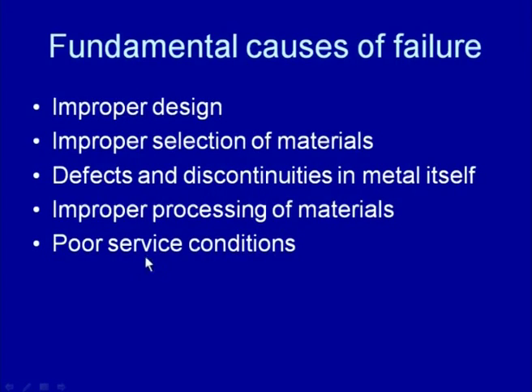Then there are poor service conditions. A component can fail if it is exposed to conditions for which it has not been designed. For example, a mild steel weld joint can be successfully used under normal ambient conditions, but if it is used under sub-zero conditions, below minus 20 degree centigrade, then it will show a great reduction in toughness, and it can fail in a very brittle manner and will not be able to perform its intended function. Similarly, if something is expected to work under ambient conditions and is exposed to high temperature, then under creep conditions it will change its dimensions, and that can lead to premature failure of the component.